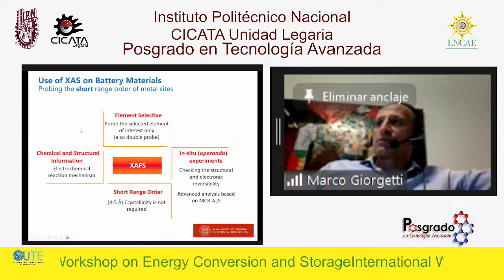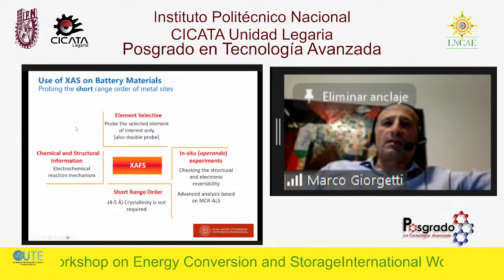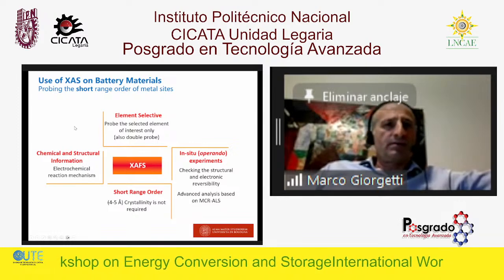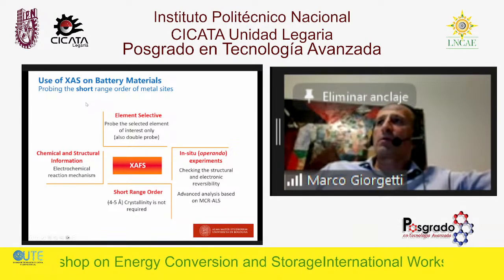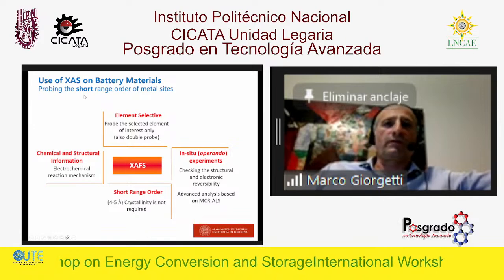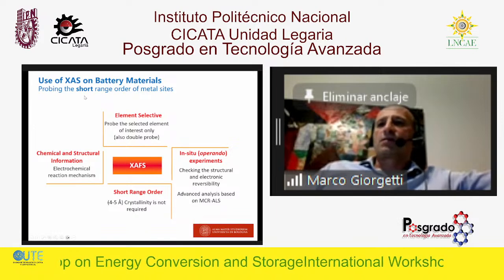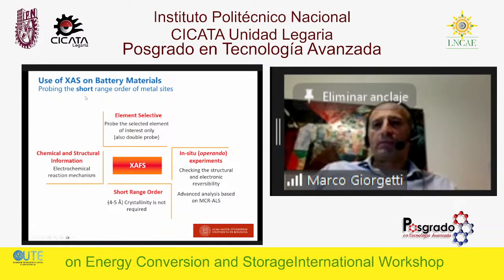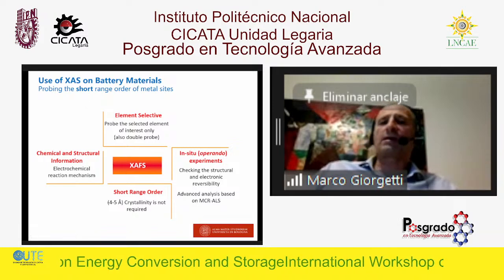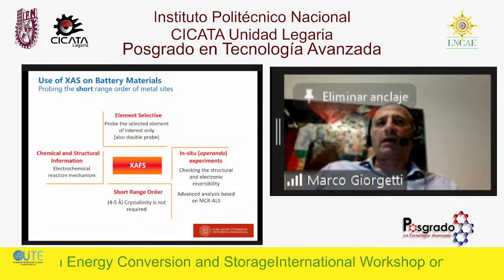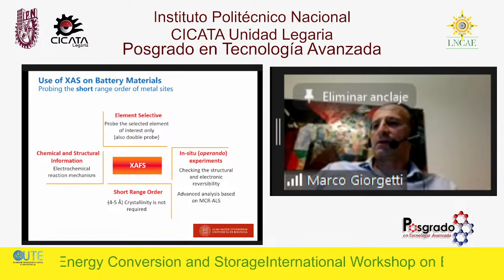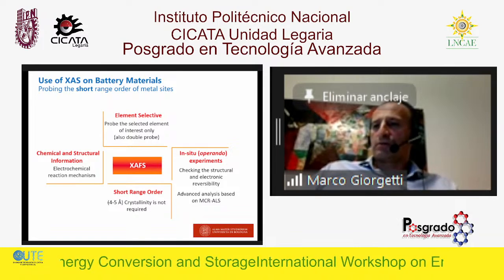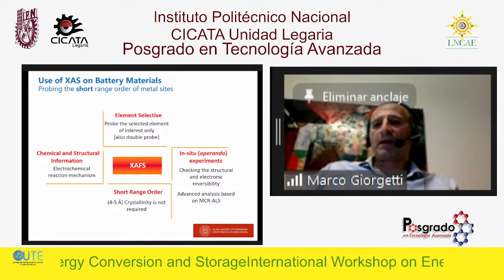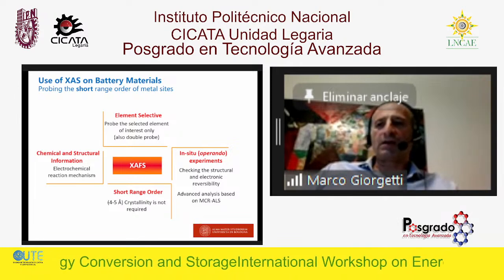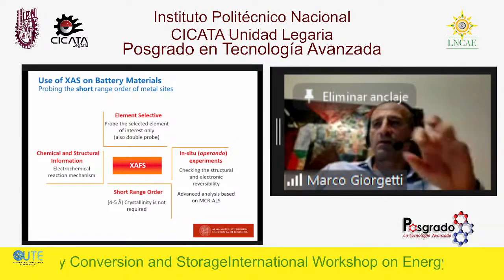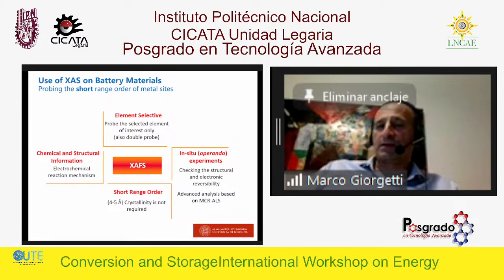Okay, the second is XAS, X-ray absorption spectroscopy, on battery materials. They are complementary, because here we probe the short-range order of the metallic site. First of all, we have to have metals that we want to check, because first we have to create a core hole and create the photoelectron from the core hole. So we have a metal, we create a core hole in that metal, and we are going to see what is around only that metal.